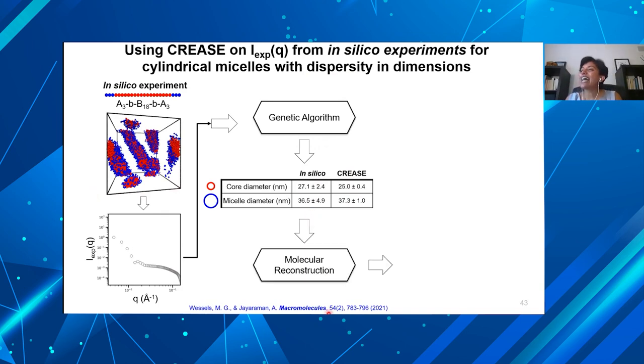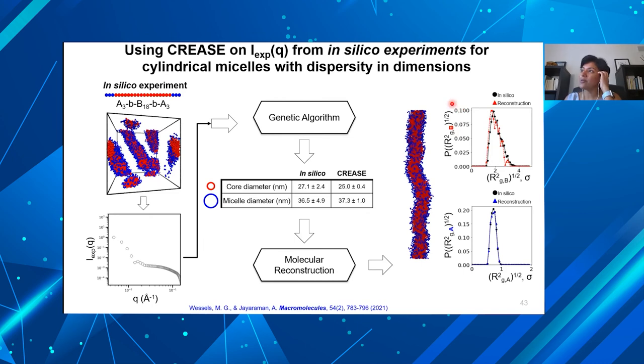The reason we did that is we wanted to show you that the molecular reconstruction agrees really well. So when we reconstruct using purely these dimensions, do we get back these conformations that we had there? And we do. So the radius of gyration of the red block and the blue block, the distributions from our reconstruction and the original experiment agree. So that's why we do such experiments to know that. We use our own scattering data from our simulated experiment.